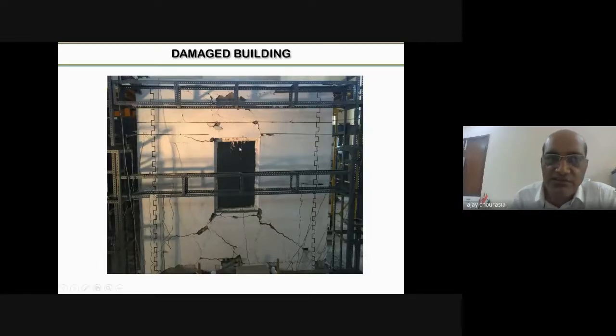Then the advantage of this particular bonding is that it provides an integral box section and provides confinement to the masonry. Even if cracks are happening, the tie columns and bond beams do not allow these cracks to propagate beyond this particular element. Even at the maximum loading, bending of the longitudinal reinforcement has been noticed. So in short, the cracks have been arrested within the wall panels. That's how you can restrict the collapse of the wall panel.